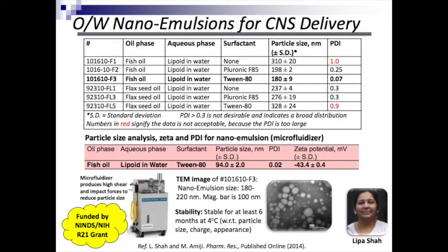The first approach that you see up here is designing the emulsions using an ultrasound approach in the lab, which can generate small volumes up to about 5 ml to 10 ml. So for lab scale, we use this ultrasound approach, basically using an ultrasound sonicator, and we can reduce the oil particle size down to between 100 and 300 nanometers, depending on formulation. The second component, so there are three components in an emulsion. It's a very versatile system.